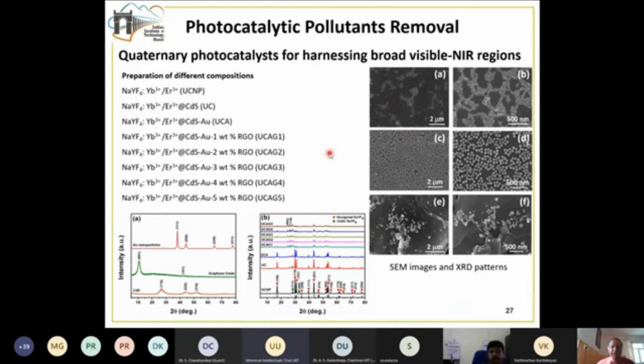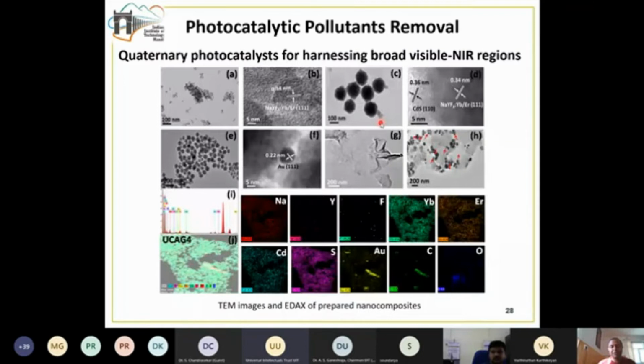So for that, we did the detailed X-ray diffraction characterization, which is shown here in these two slides. And we could clearly see that our material synthesis is successful. Then from the SEM investigations, we were able to see the monodispersity of the particles which are formed. You can see that the particles are almost monodispersed, and this is for the nanocomposite. And further morphological information was obtained from TEM analysis, wherein we could clearly see this core-shell type of structure, wherein the dark colored internal region is the core, and the light colored one, which is the cadmium sulfide, is the shell. And this is for the overall nanocomposite.